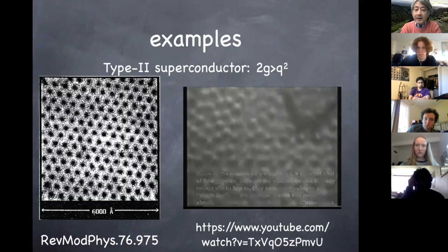So what you have seen is that these fluxons, the Abrikosov flux punching through a thin film of superconductor, are now dynamical. They can move around. And if the film has a defect in it, as the first part of the video showed, defects tend to attract those vortices. The vortices get trapped where the defects are. But once you have more and more vortices coming into the system, not all of them can occupy the position of the defects.